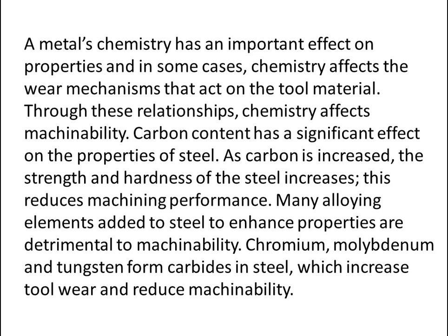A metal's chemistry has an important effect on properties, and in some cases chemistry affects the wear mechanisms that act on the tool material. Through these relationships, chemistry affects machinability. Carbon content has a significant effect on the properties of steel — as carbon is increased, the strength and hardness of the steel increase, which reduces machining performance. Many alloying elements added to steel to enhance properties are detrimental to machinability. Chromium, molybdenum, and tungsten form carbides in steel, which increase tool wear and reduce machinability.